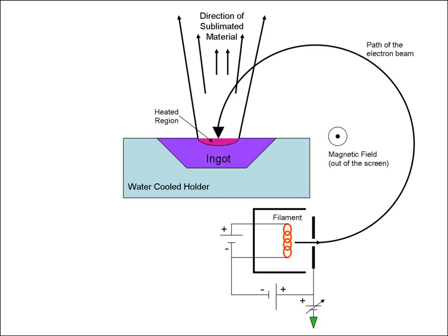Accelerating voltages can be between 3 and 40 kilovolts. When the accelerating voltage is 20 to 25 kilovolts and the beam current is a few amperes, 85% of the electrons' kinetic energy can be converted into thermal energy. Some of the incident electron energy is lost through the production of X-rays and secondary electron emission.